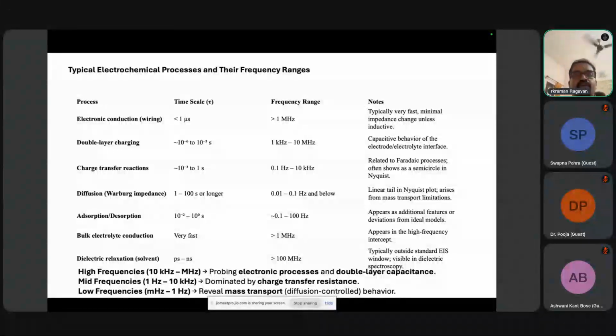So now if you see, this is a Faraday process. They respond in the frequency range 0.1 hertz to 10 kilohertz. And now if you look at the diffusion, many of you know the word Warburg impedance. The diffusion response happens in 1 to 100 seconds or longer. So that is 0.01 to 0.1 hertz, a region where you would see them respond.